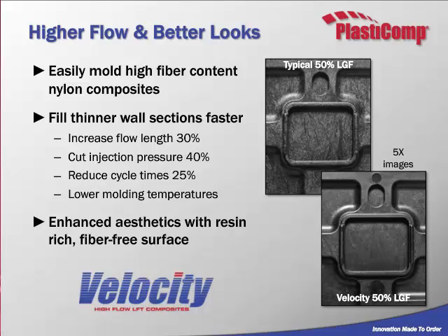Another development that we've had is a product that we call Velocity. And what this grade gives you is higher flow, better aesthetics at lower temperatures. One knock on long fiber materials, and especially high loading long fiber materials, is that at times you can get surfaces that are not as desirable as you'd see in a lower fill content.